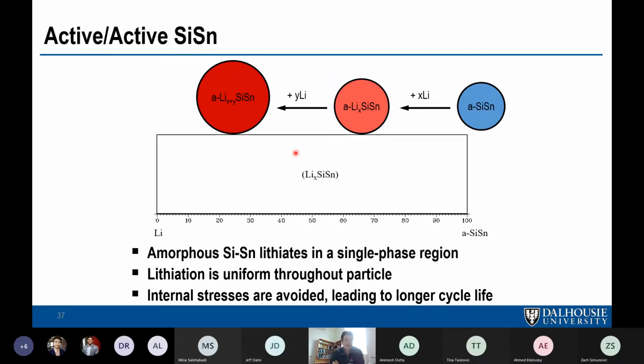So one of the strategies in this field has been to make things either completely amorphous or small enough that there aren't basically enough atoms to form these big unit cells for these lithiated phases. And if you can't form the crystalline structure because you don't have enough atoms, well, you can't be in a 2-phase region, and you end up being in a single phase region. And in these single phase regions, you get a continuous lithiation of the particle. And so the particle can expand evenly. At least that's the idea. Of course, you could get composition gradients and get strain that way. But, you know, it's a lot more reversible. And then if you take lithium out and you're still in a single phase region, then the particle can delithiate uniformly and uniformly shrink, avoiding these internal stresses and fracture.